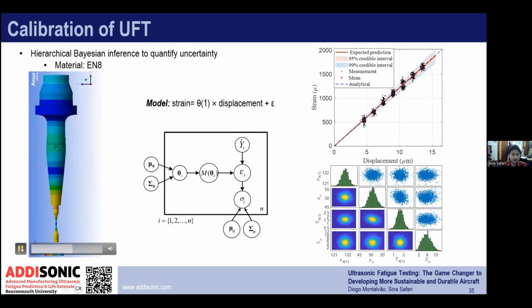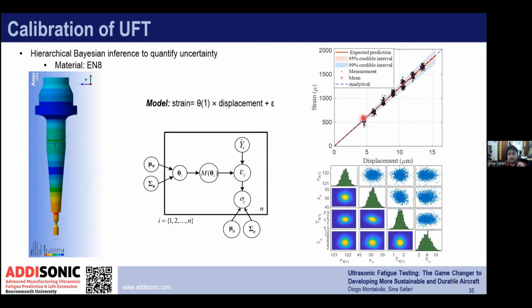So this slide is about how we build the relationship between the tip displacement and the strain in the middle, which we can calculate the stress from, because there are some uncertainties involved. As you can see in this figure, I collected some data points for different displacements at the tip, in the top right. For example, just below 5 micrometer, I excite the system, I measure the tip displacement using laser, and using the camera, I measure the strain. I repeat this process many times and collected many data for each tip displacement, or let's say operational level of the machine.